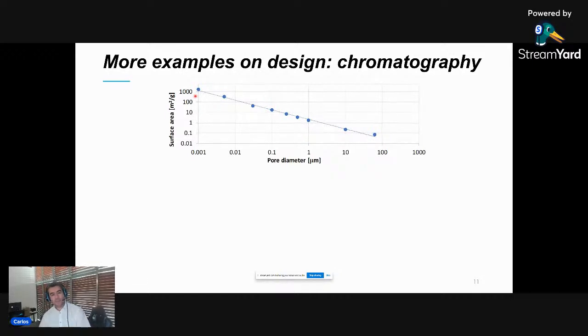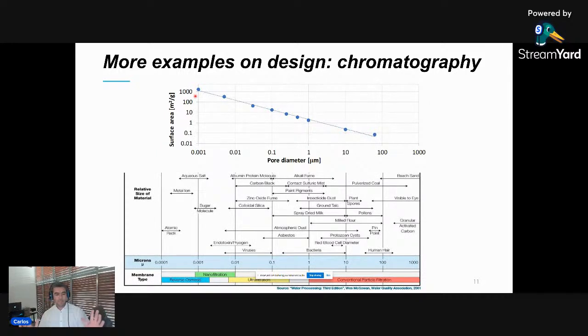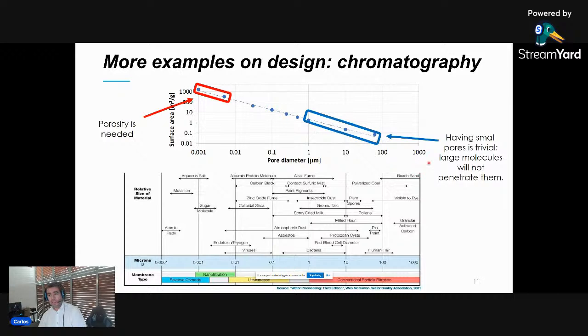The interesting part when you do something like that is that if you start correlating with things that you can find in nature, you will see that, for example, for using adsorbents for making small separations like sugars, gas separation, metallic ions, you're around these values of molecules of pore needed. So you will need porosity to perform a more efficient separation. But for example, if you go to work in the bio area with red blood cells and bacteria, and to some extent some viruses, it doesn't really matter if you have pores.